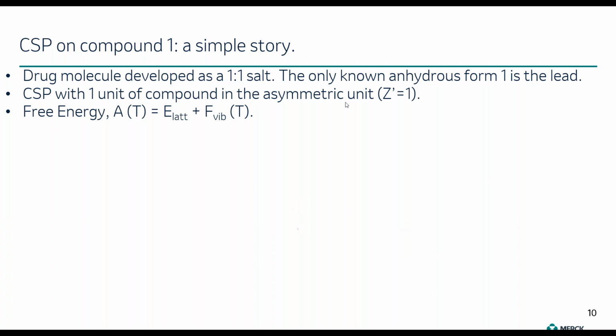We performed CSP studies with 1 unit of the compound in the asymmetric unit cell, or Z'=1 using crystallographic notation. And we also calculated the free energies at finite temperatures for some of the predicted crystal structures by adding to the lattice energy the vibrational component of the free energy, calculated with the harmonic approximation.